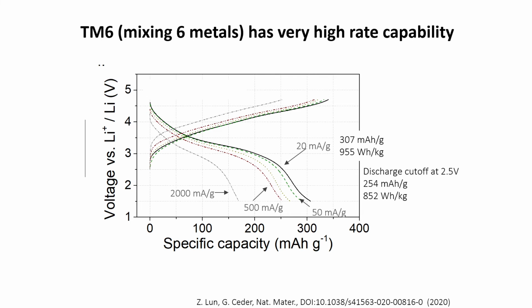These materials also have extremely good rate performance. This is more of a side issue, but rate performance, which is the ability to charge and discharge fast, depends on the diffusivity. And here we can discharge at 2,000 milliamps per gram, which is something like a full charge or discharge in 5 to 6 minutes, which is remarkable for a battery material.